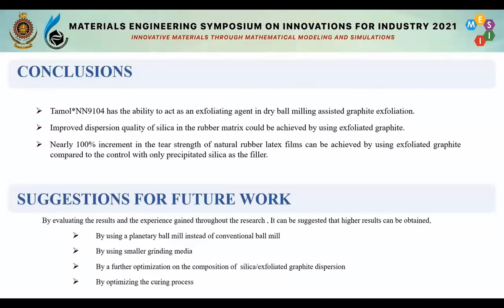And also the preparation technique of the silica and exfoliated graphite aqueous dispersion can be optimized, which will directly affect the final results. And finally, the curing process of the rubber latex films can also be optimized. When we introduce graphite into the natural rubber latex matrix, it is a known fact that the thermal conductivity properties of the final rubber vulcanizate will be different. Therefore, it is possible to use this as further detailed research.